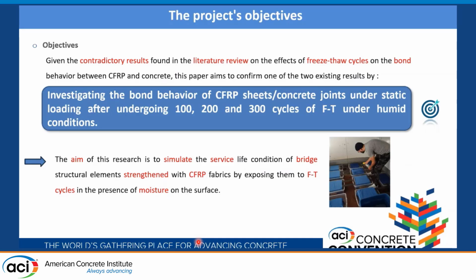So, given the contradictory results found in the literature review on the effects of freeze-thaw cycles on the bond between CFRP and concrete, this paper aims to confirm one of the two existing results by investigating the bond behavior of CFRP sheet concrete joints under static loading after 100, 200, and 300 cycles of freeze-thaw in humid conditions. The aim of this research is to simulate the service life conditions of bridge structural elements strengthened with CFRP fabrics by exposing them to freeze-thaw cycles in the presence of moisture on the surface.